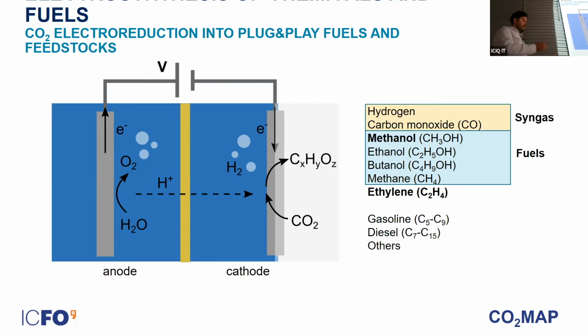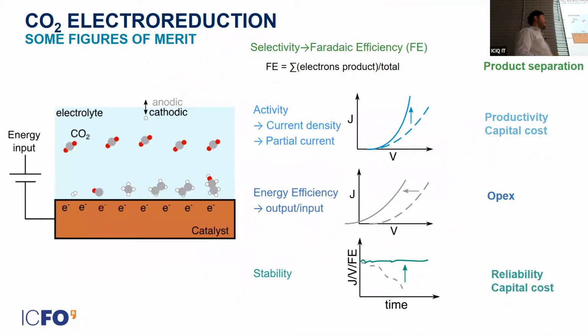Now you could make many things, but this means that you have to be careful with the metrics of these efficiencies. So I'll just briefly introduce some of the numbers that we will be talking about during this talk. You can see here a substrate, the catalyst, CO2 molecules, and examples of different products in principle. One very important figure of merit in these CO2 electrolysis systems is selectivity. This is often referred to as Faradaic efficiency, which conveys the fraction of electrons that are used for a given molecule. So for example, if you have a 25% Faradaic efficiency towards methane, that means that 25% of your electrons are used to generate methane.